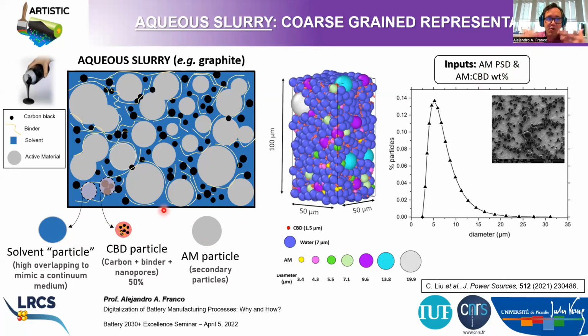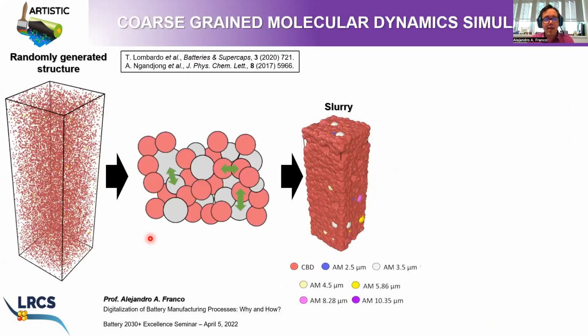The difference with the non-aqueous slurry is that in this approach, the CBD particles don't contain solvent, right? They only contain carbon binder and some nanoporosity inside, because the solvent is described by itself as a single type of particle, right? Then how does this technique work, the coarse grain molecular dynamics approach to simulate slurries?